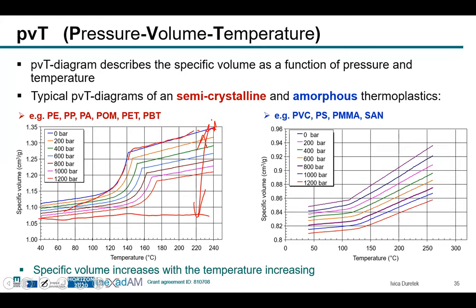printed layer, between laying down the material and solidifying at room temperature. Layers, because the first layer is, for example, in solid state, and the next layer is in the melted state. And in the contact between the layers, you have different temperatures and different shrinkage.